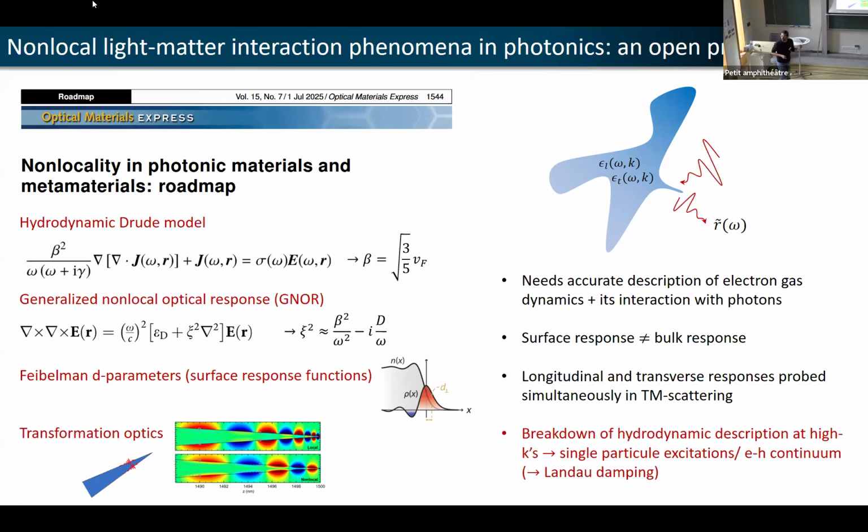Well, I mean, naively, can't I just, as a first attempt, calculate some high temperature equivalent of a Lindhard function, like what we have for a degenerate electron gas? Yes. So they do, actually. If you get the Lindhard function, it can be complicated because you have logs in there. So actually they do the first leading order correction to the local response, which is basically when you take the first spatial derivative. So they call it the hydrodynamic Drude model, for example. This is just the leading correction.